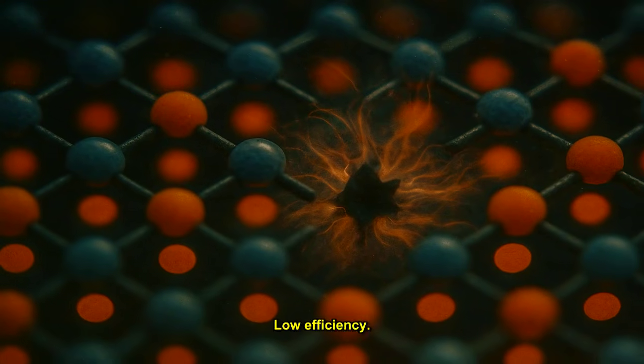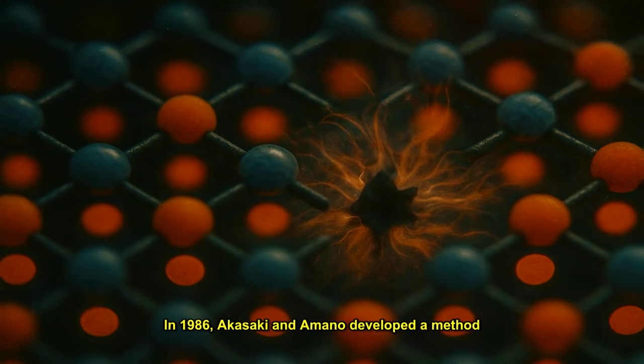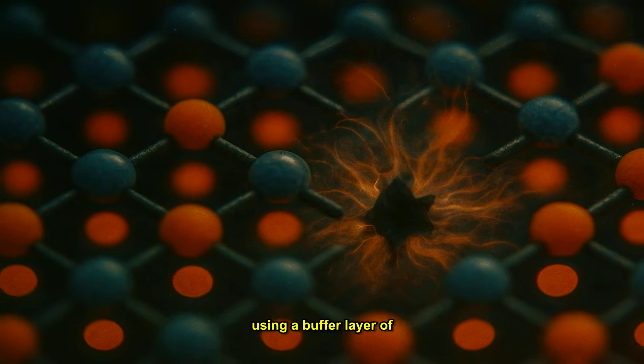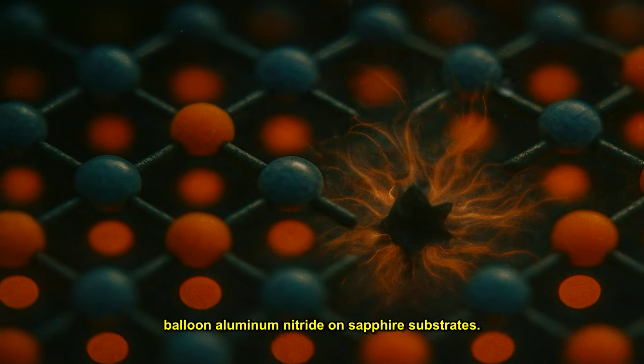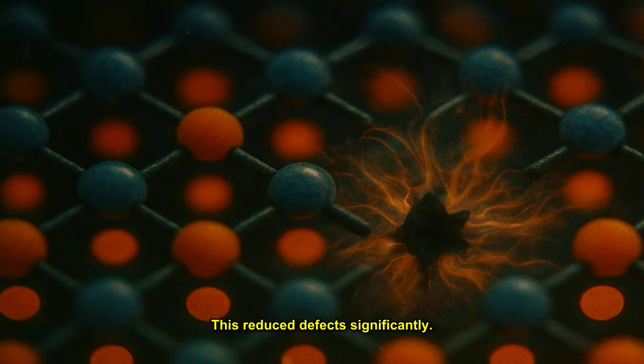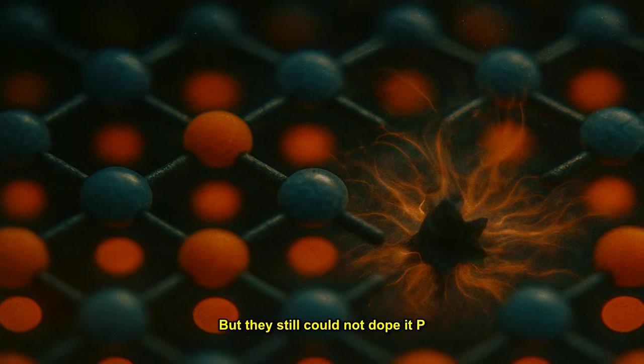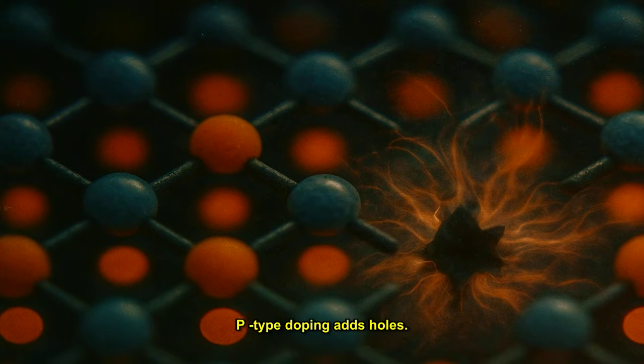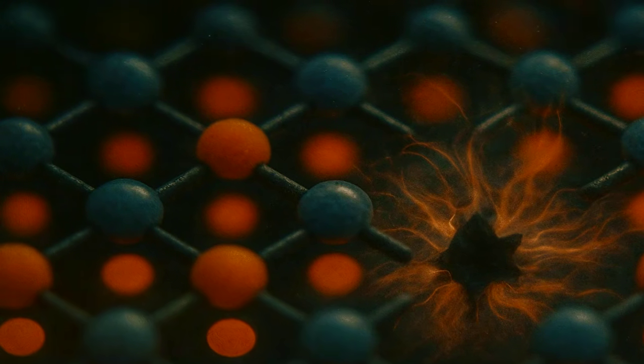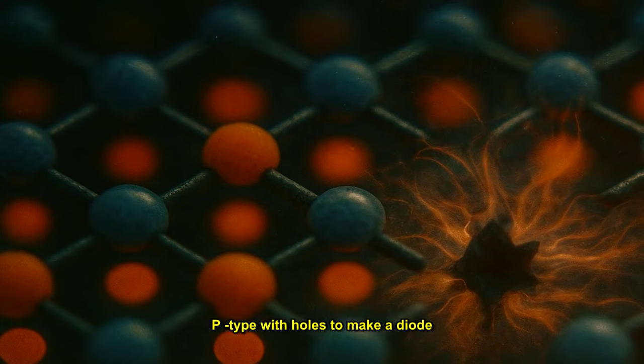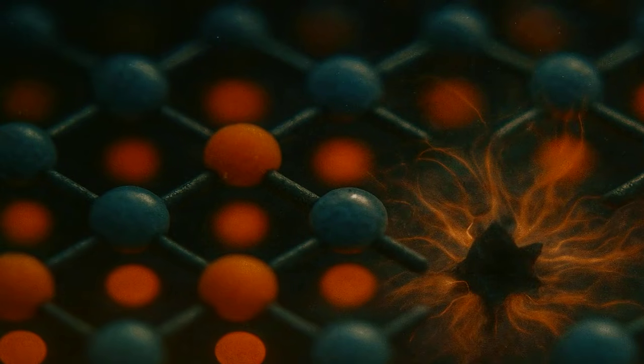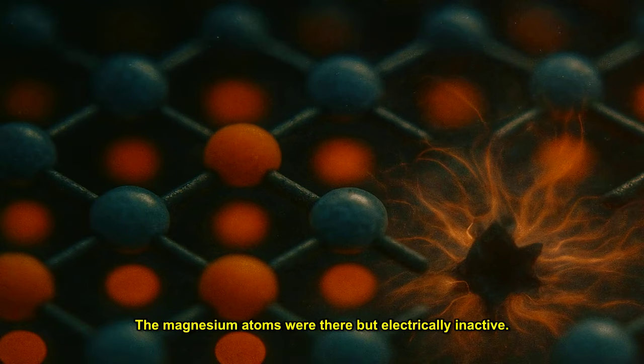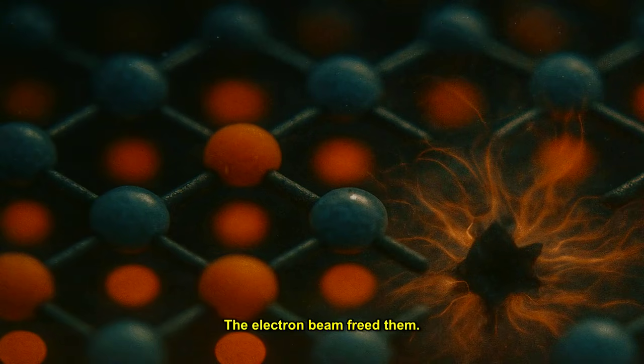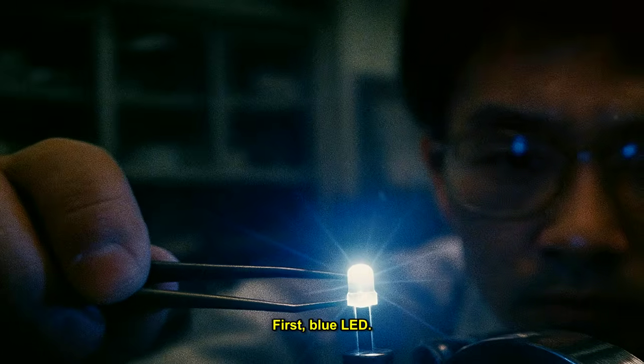Wasted energy, low efficiency. In 1986, Akasaki and Amano developed a method using a buffer layer of aluminum nitride on sapphire substrates. This reduced defects significantly, but they still could not dope it p-type effectively. P-type doping adds holes. You need both n-type with electrons and p-type with holes to make a diode junction. Doping. The magnesium atoms were there, but electrically inactive. The electron beam freed them. First, blue LED.